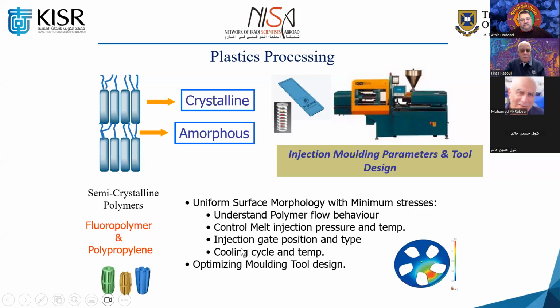Of course, the cooling is important in any processing. You don't want to cool your polymer so quickly and suddenly. You need it to cool gradually, in order to balance between the crystalline phase and the amorphous phase. A crystalline phase usually does not graft very well. If you want to put a polymer and graft it on that, it is very hard to graft on a crystalline phase. So the grafting usually happens on an amorphous phase of the polymer,